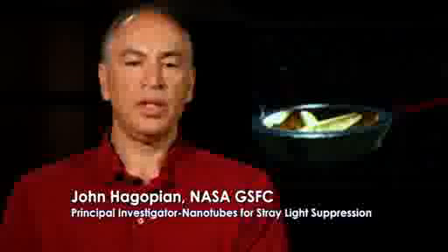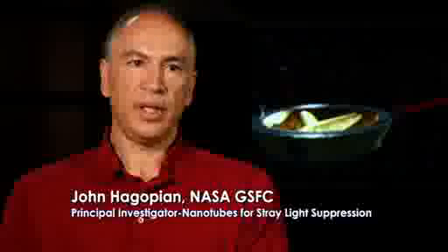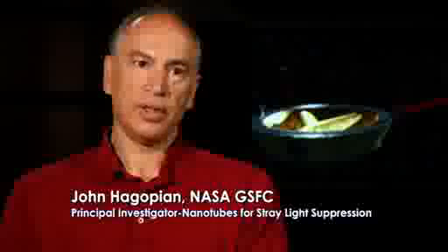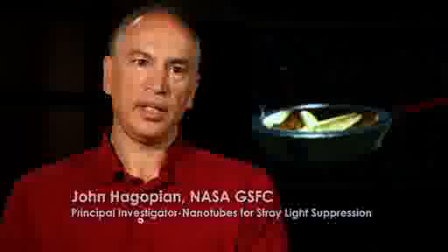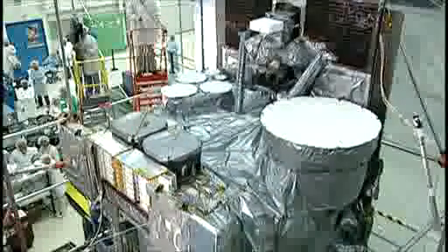Over a long period of time after all these experiments, we discovered that alumina is really the trick to getting the nanotubes to stick. So now you can't scratch them off. They're very robust.